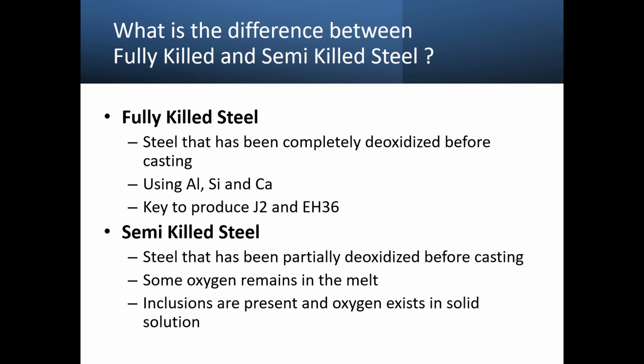A semi-killed steel means that it has been partially deoxidized before casting. So some oxygen does remain in the melt. In other words, oxygen actually is in solid solution in the steel. And also inclusions such as aluminum oxide and silicon oxide are present in the steel.